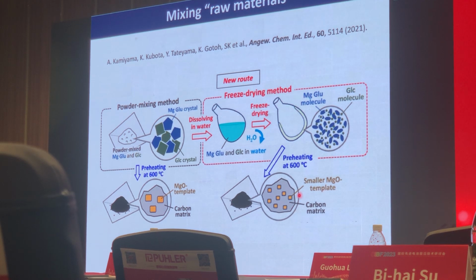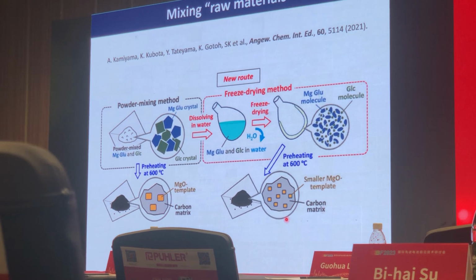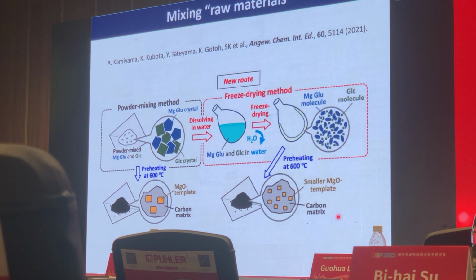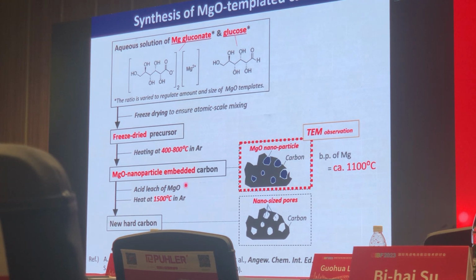Then we have highly dispersed magnesium oxide template in the carbon matrix. And after post-heat treatment of this precursor, we have very high capacity hard carbon for sodium-ion battery. So the synthetic route is like that. The glucose and magnesium gluconate were homogeneously mixed through the freeze-drying process, and then we have nano-sized pores inside the carbon matrix. Then finally, by post-heat treatment at 1,500 degrees C, we successfully prepared the new high-capacity hard carbon.